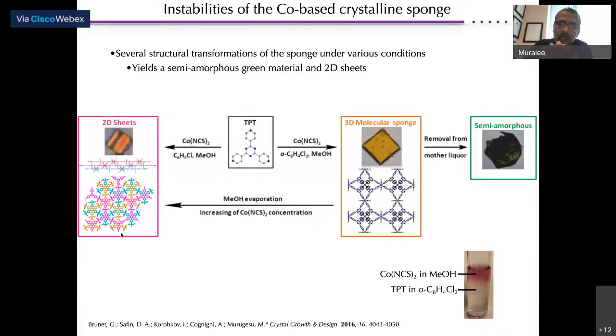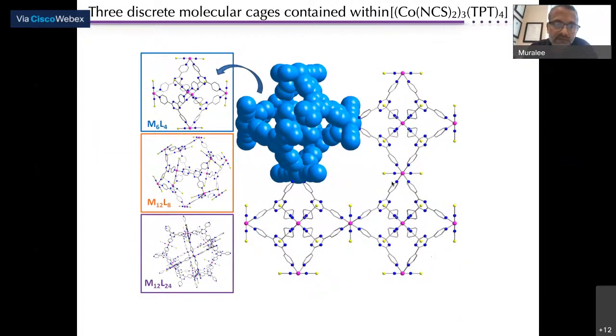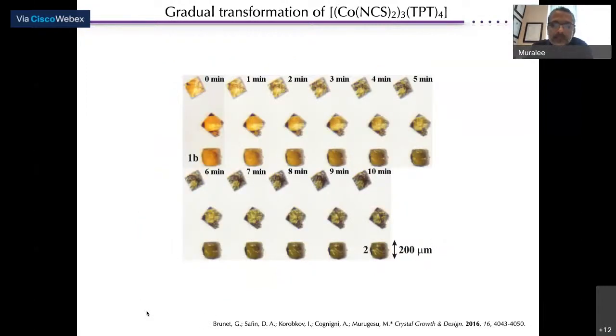Basically, it's a two-dimensional framework where the sheets are slightly moved from each other and form this two-dimensional framework stacked on top of each other. You can isolate the single crystals also using chlorobenzene instead of the dichlorobenzene, and isolate the nice single crystal of it. This is the methodology for crystallizing, and this is nothing new. This is a report. So the framework itself has the different units of these SBUs. You can see M6L4 unit or M12L8, or even much larger unit that can act as a cavity for gas molecules. But if you want to do crystalline sponge method, we need a system that is stable.